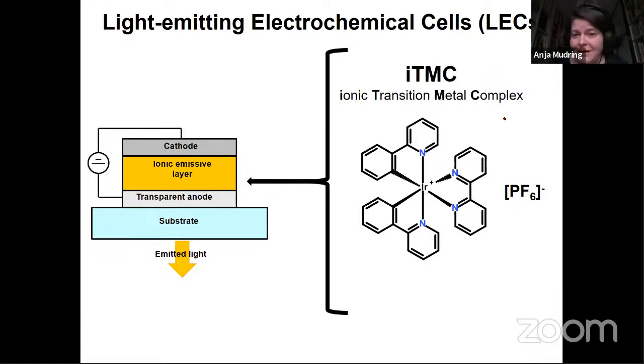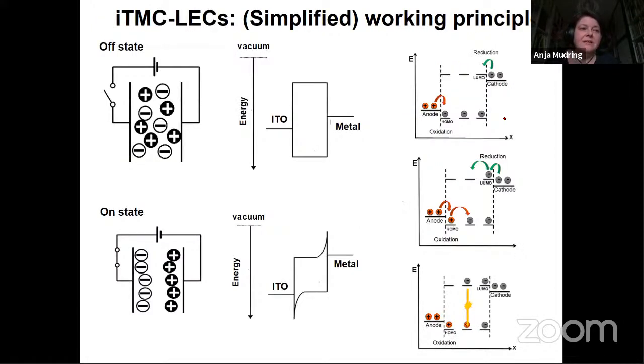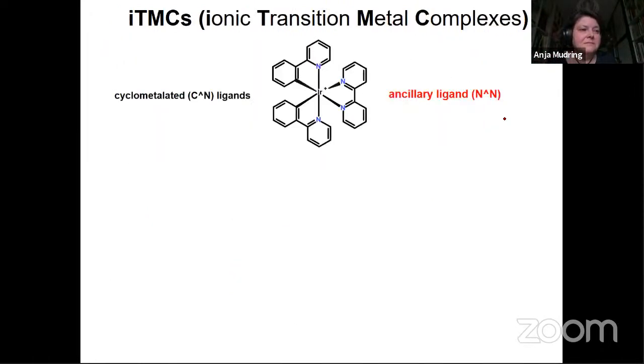And you just need a light emissive electrolyte, an ionic liquid. And that's why we now engaged in the synthesis of metal-containing ionic liquids, where the cation, in this case here, the iridium cation, sends out light. Basically, you play around with the HOMO and LUMO of your charge transition metal complex, and like in an LED, you oxidize and reduce it. So you inject electrons and holes, they migrate through electron transfer now, and in the emissive zone, the light gets emitted.